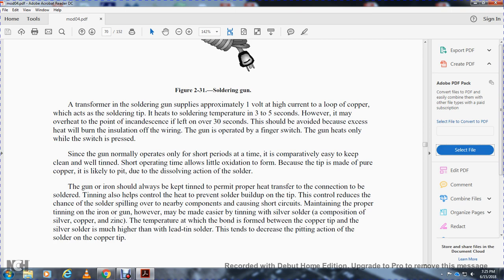Because the tip is made of pure copper, it is likely to pit due to the dissolving action of solder. The gun and iron should always be kept tinned to permit proper heat transfer. The connection should be made with solder tinning. It also helps to control the heat and prevent solder buildup on the tip. The control reduces the chance of solder spilling over nearby components, causing short circuits.